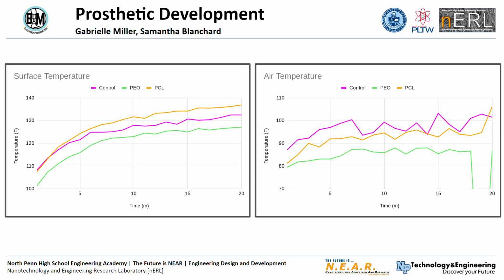So overall, our PEO was on average 5 degrees cooler on the surface and 11 degrees cooler in the air. While it did not perform in the heat sink fashion that we anticipated, it was overall successful in keeping our entire system cool and would be applicable for our use. PCL, on the other hand, kept the surface about 3 degrees warmer and the air temperature about 5 degrees cooler, meaning instead of pulling heat away from the surface, it trapped the heat inside like a blanket.